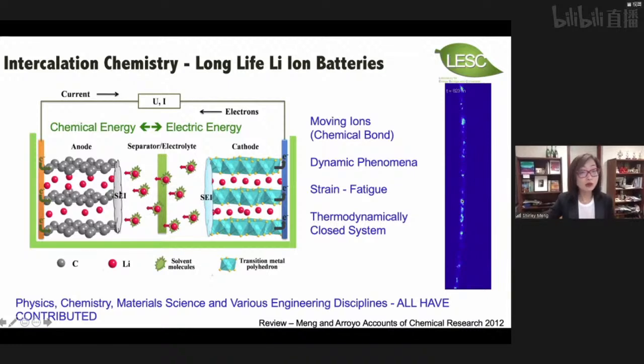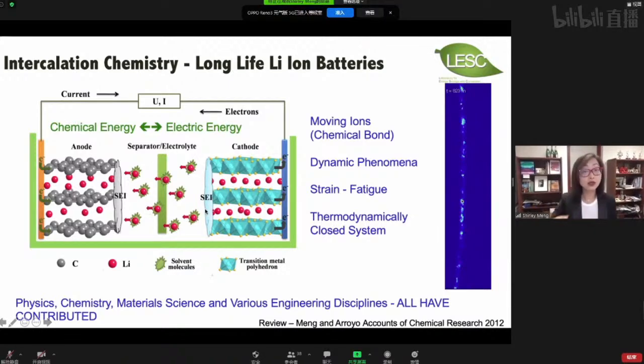And as we're moving away from intercalation chemistry, for example, the carbon, which is a layered structure, this carbon is going to be replaced by silicon or lithium metal. These are not intercalation materials anymore. So how can you ensure the electrolyte is still compatible with the new types of anode or cathode materials is a really, really big question.